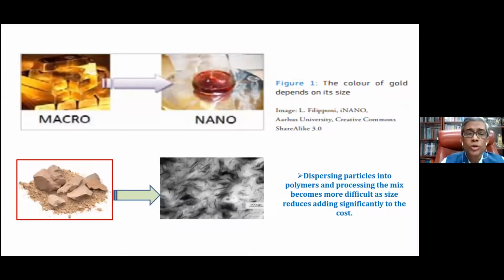Okay, so what we need to do is to develop technology by which you can disperse this particle, and then it becomes like this size, and then it may even become a transparent one. Okay, so the better you can disperse, the better you can separate them out, this will give a different property, and each and every one is at nano level, which has been looked into by transmission electron microscope. You can see this. So there is a sea change in the color and the morphology and the structure as we change.